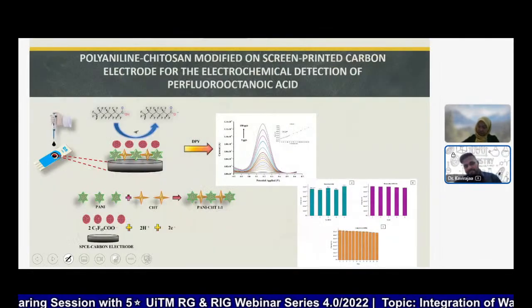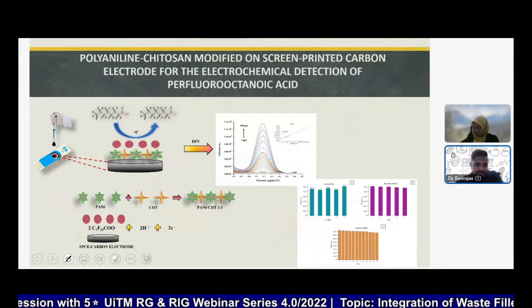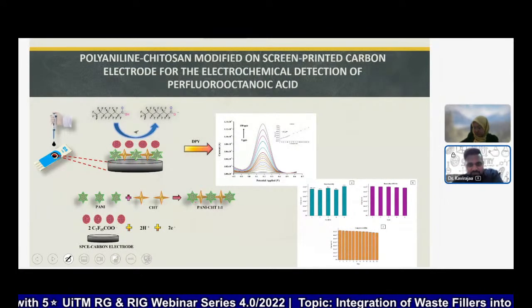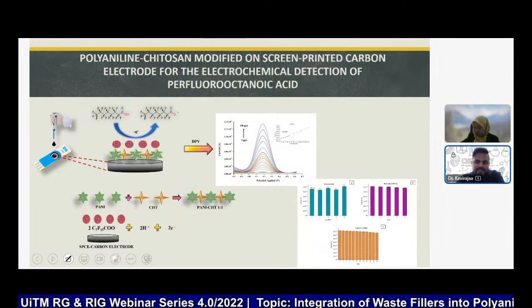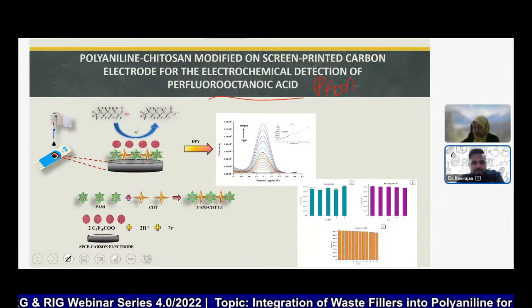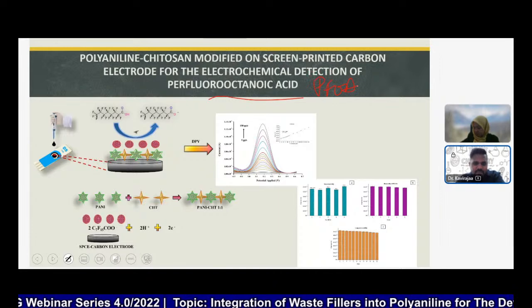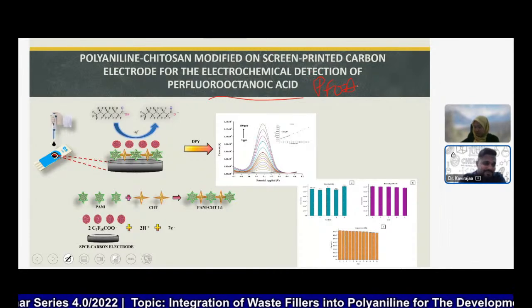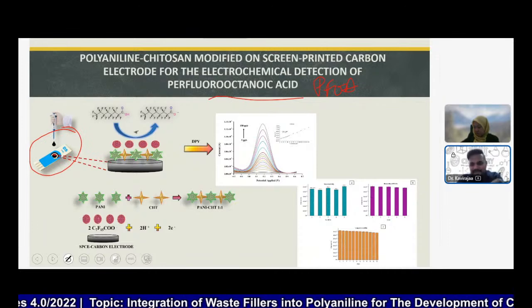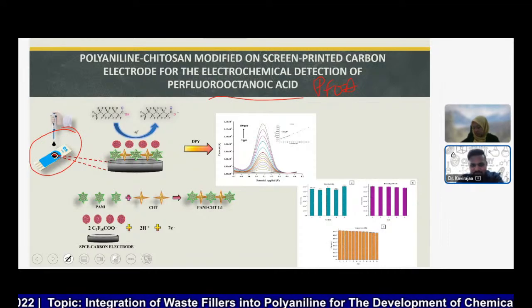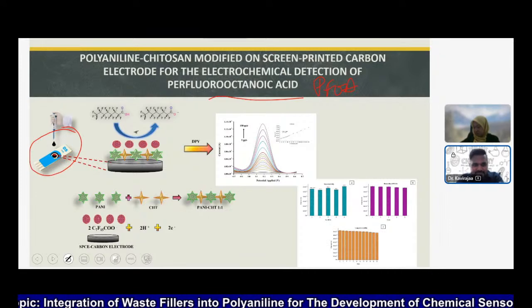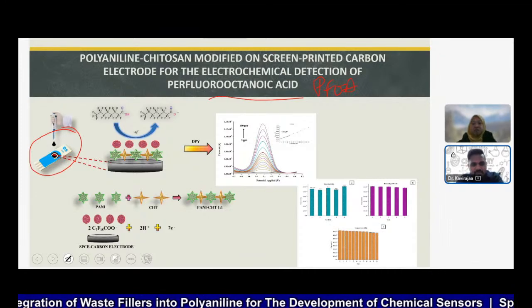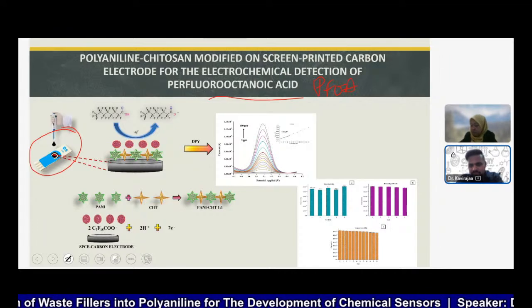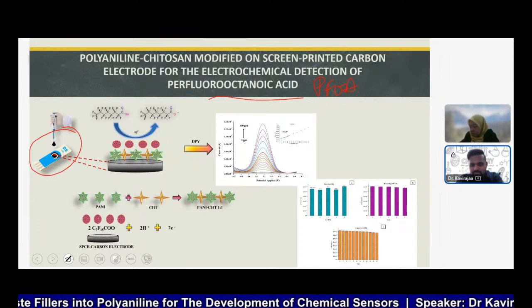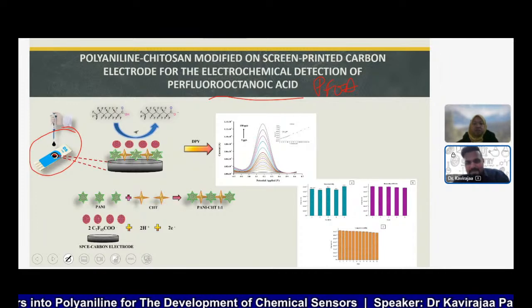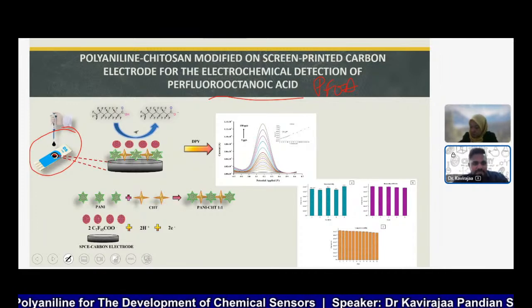Okay, so this is our study where we developed a polyaniline chitosan modified screen printed carbon electrode for the electrochemical detection of perfluorooctanoic acid, which is PFOA. In short, we don't want to use expensive electrodes, so we just went for the SPC. It's not to say cheap, but this project was funded, so we got some money to buy these screen printed electrodes. This is a master's work, so we had the time, even though it was affected by the pandemic. So we developed an in situ based polyaniline chitosan.